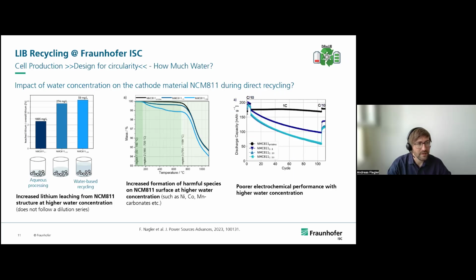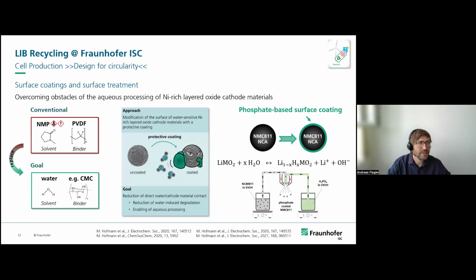we looked at the water content, so how much water affects the leaching process. So we start with a ratio of 1:1, like in the aqueous processing step. And we see that we have a lot of leaching, and when we increase the amount, we reach a saturated phase. So in a water-based process, we have a saturated region, and we see that we have a lot of coatings like carbonates on the active materials, and this gives a poor performance in the electrochemical behavior. So to prevent this issue, we coat the active material with a phosphate-based coating. Here we use the method of spray drying. And with this water-based process, we can use water as solvent and also a water-soluble binder like CMC.